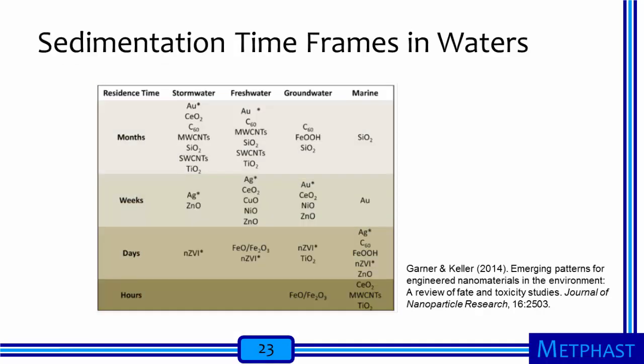The same authors classified timeframes for sedimentation for various engineered nanomaterials in different types of aquatic systems. The trends were similar, though not identical, to the aggregation timeframes. In general, sedimentation was fastest in seawater compared to stormwater, freshwater, and groundwater. Zero-valent iron and iron 2-3 oxide nanoparticles generally showed the fastest sedimentation rates across all of the aquatic systems. However, cerium oxide nanoparticles, multi-walled carbon nanotubes, and nanotitanium dioxide all demonstrated sedimentation timeframes of just hours in seawater.